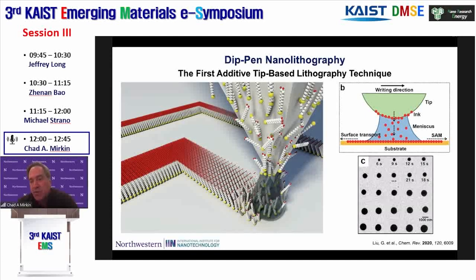We were studying water transport at the time, what's known as the capillary effect, and the fact that when you run an AFM experiment in air, water collects at the point of contact, and that water moves with the tip, and either moves up or down it, depending upon the relative hydrophobicities of the tip and substrate. And what it allowed you to do was to create metastable patterns of water that would eventually fade back to equilibrium when you remove the tip.